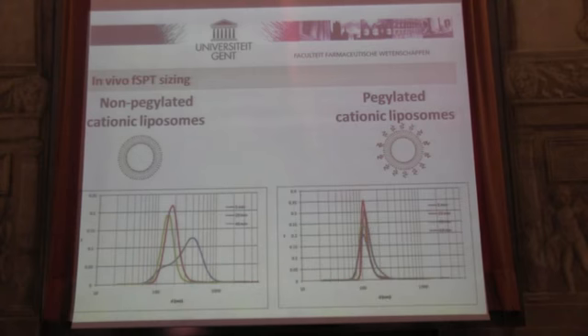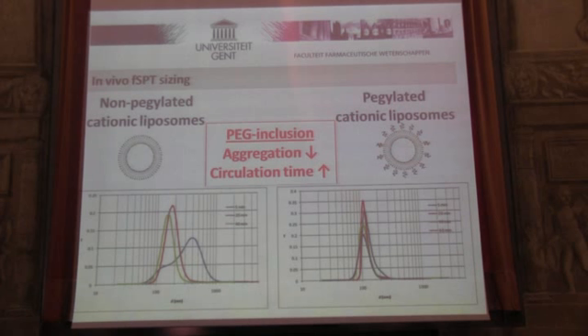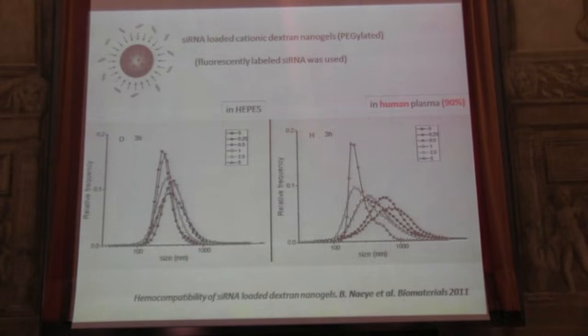The pegylated ones, indeed, they remained stable, no aggregation, also not at initial time points, and it keeps stable for a long time period. So PEG decreases aggregation, as one would expect, but we can measure it, and it improves the circulation time. I will come back to that. And to show you that this is not limited to liposomes, this was a study on cationic dextran nanogels in which siRNA was included. Also here, this was in plasma, you see as a function of the pegylation degree that you keep the particle more stable if you include more PEG.